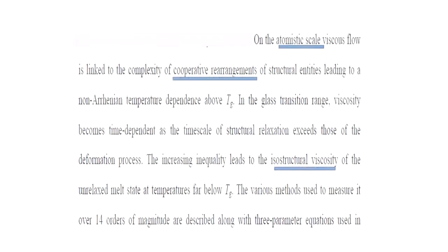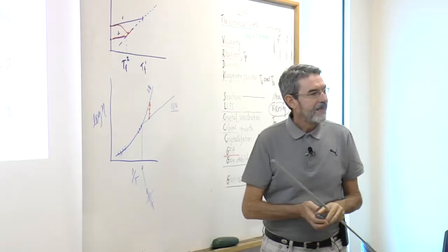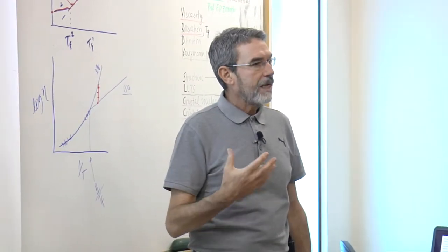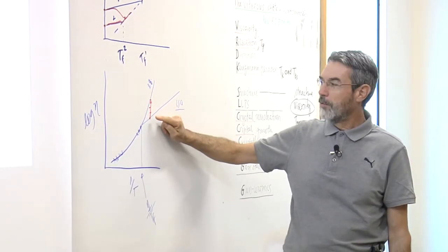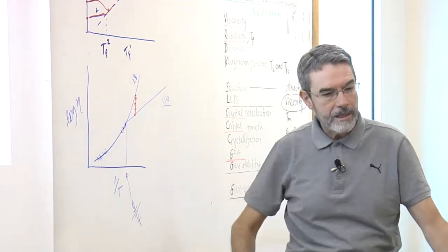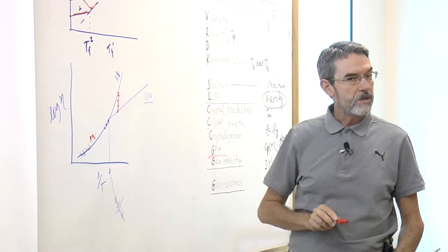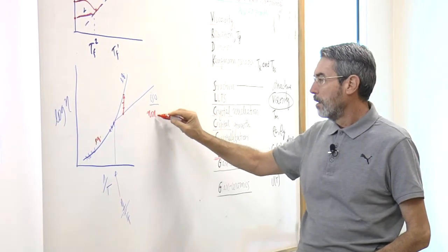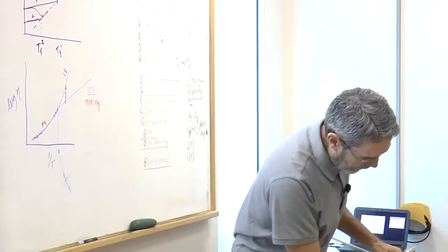let's go back. So I was talking about then isostructural viscosity. So the supercooled liquid is frozen. As I explained last week, frozen means only a temporary state. So a glass is a rigid material, is not a solid, which is frozen. But we can unfreeze a glass by heating it. And we will relax and go to the equilibrium viscosity. So the curve that we have here at high temperatures, above Tg, is always the equilibrium viscosity, because the liquid had time enough to relax during the measurement. It becomes non-equilibrium, so iso or non-equilibrium viscosity below the fictive temperature of the material. All right.